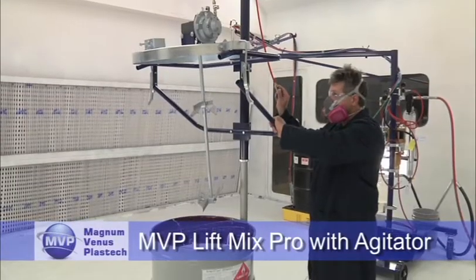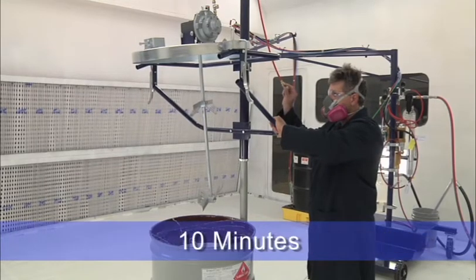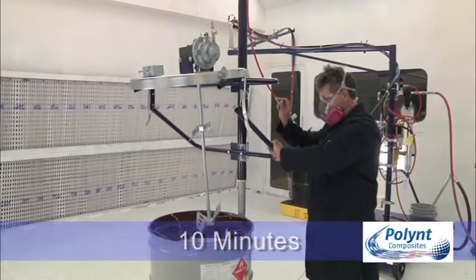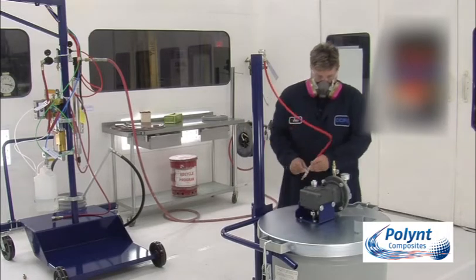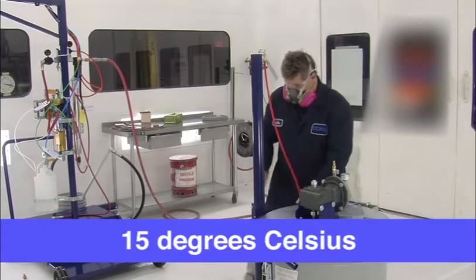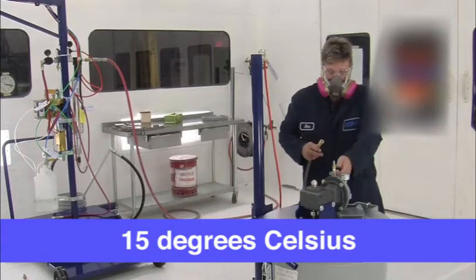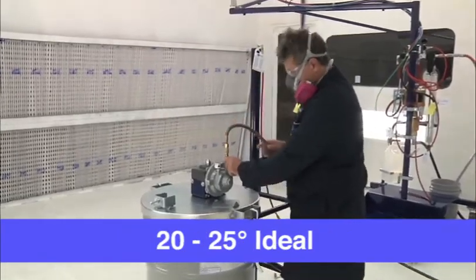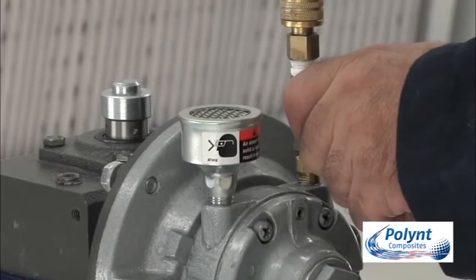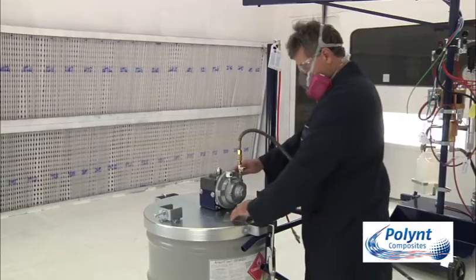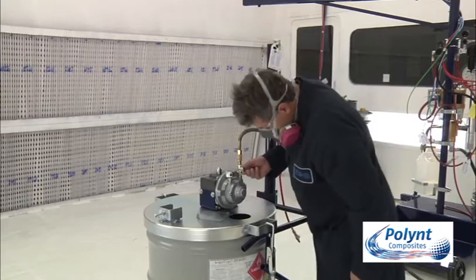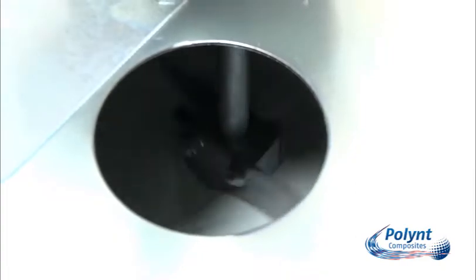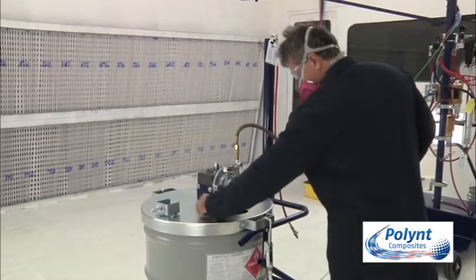Mix gel coat for 10 minutes prior to use, but do not overmix. Overmixing causes breakdown of gel coat viscosity, increasing the risk of sagging and porosity. Make sure that the material, mould and ambient temperature is 15 degrees Celsius or greater. 20 to 25 degrees Celsius is ideal for gel coat application. When gel coat is below 15 degrees Celsius, viscosity, thixotropy and cure are affected. This changes flow rates, atomization and increases the tendency to sag. In warmer conditions, working time may be shorter. Only use material within its recommended shelf life.